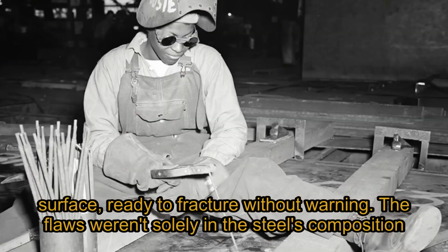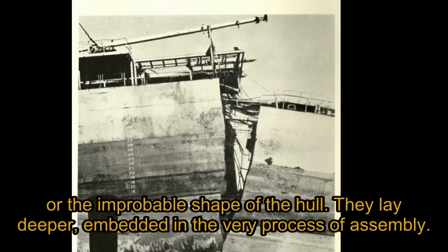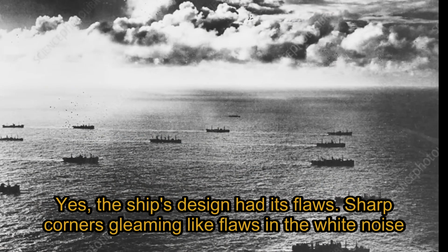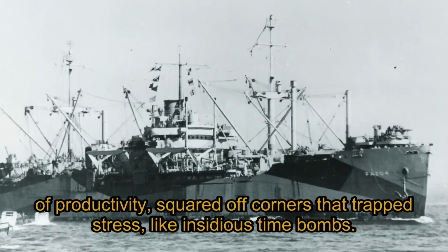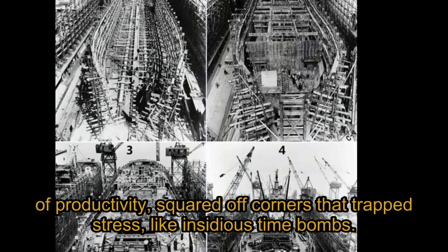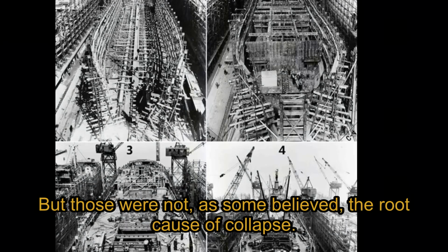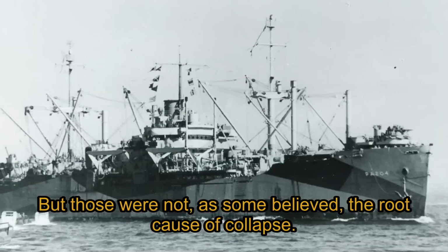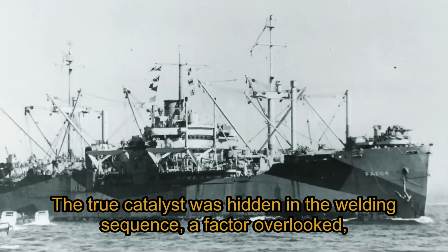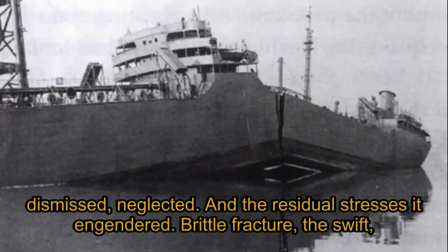The flaws weren't solely in the steel's composition or the improbable shape of the hull. They lay deeper, embedded in the very process of assembly. Yes, the ship's design had its flaws, sharp, squared-off corners that trapped stress like insidious time bombs. But those were not, as some believed, the root cause of collapse. The true catalyst was hidden in the welding sequence, a factor overlooked, dismissed, neglected, and the residual stresses it engendered.